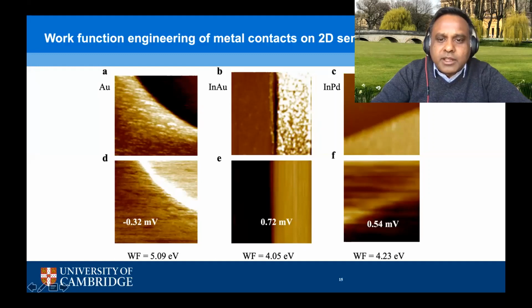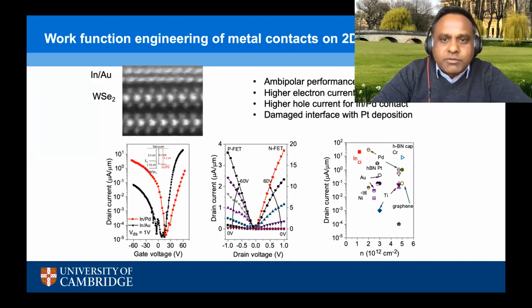So we've carried out some Kelvin probe force measurements for work function extraction. And what we found is that pure gold has, of course, a work function of 5. When we mix the indium, because it's the indium that's primarily interacting with the 2D semiconductor, the work function decreases down to around 4.05. But if we alloy the indium with palladium, we're able to increase the work function to around 4.23. And we wanted to see if this higher work function translated into different device characteristics.